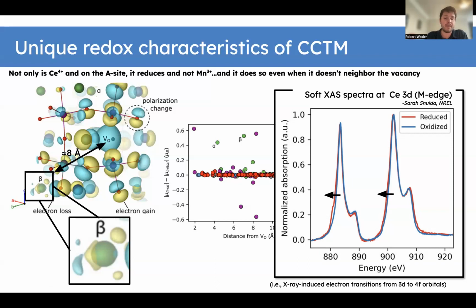We don't see a similar feature in manganese, suggesting that it is only ceria that is really reducing, which is, again, really incredible. DFT with semi-local exchange correlation and Hubbard U corrections, which is just some fancy lingo for trying to make DFT better at doing redox, tends to be qualitatively predictive for trends, but in this case, we were able to predict a structure, it was made. We were able to show that it could split water, and that bore out in experiment. And here, where really DFT could potentially break down in redox and electron redistribution, it suggested that cerium reduces, and that actually bore out in the experiment as well.